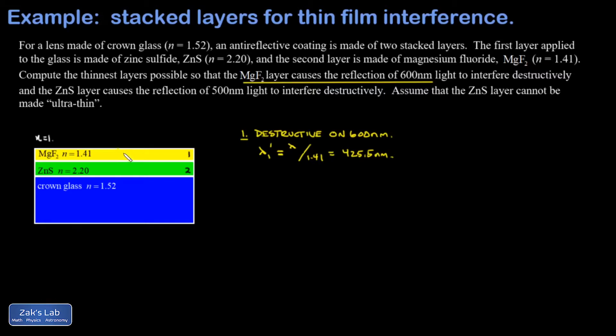Then I start thinking about the reflections at the upper surface of this thin film and at the interface with the next thin film. Our first reflection is phase shifted at the reflection because it's a transition from a faster medium into a slower medium for the light. My second reflection, that's light that penetrated through the thin film and is now reflecting off the interface with the zinc sulfide, is also phase shifted by the reflection because I went from a faster material into a slower material.